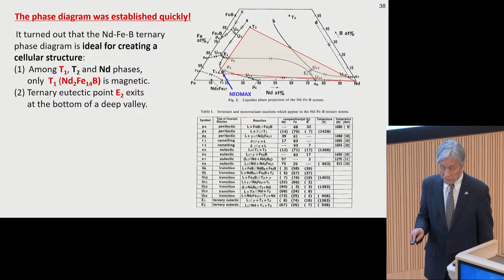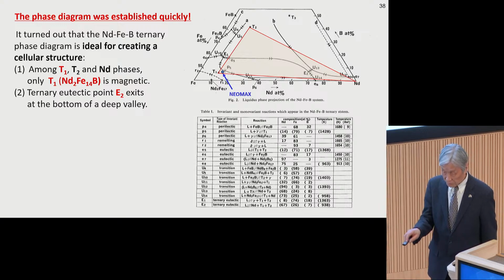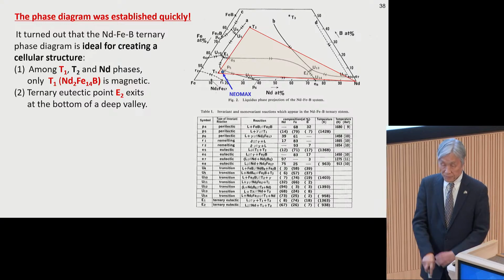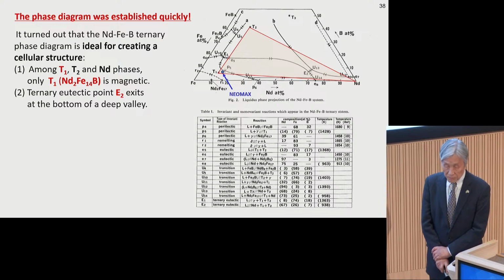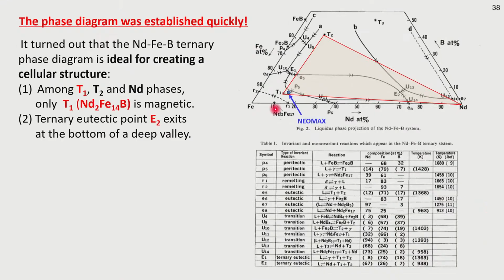And it turns out this is the iron neodymium boron ternary phase diagram, and this is ideal in this sense. First, among T1, this is the Neomax composition, and T1, T2, and neodymium, among these three compounds, only the T1 is magnetic, and the T2 and neodymium are non-magnetic. This is important to get good coercivity. And the second factor is the ternary eutectic point E2.